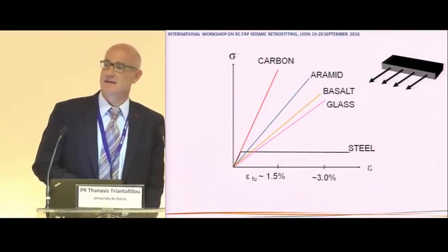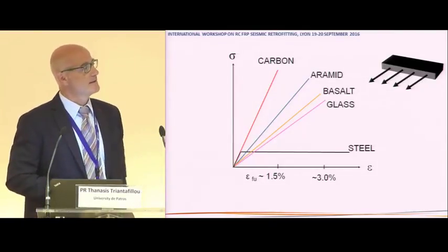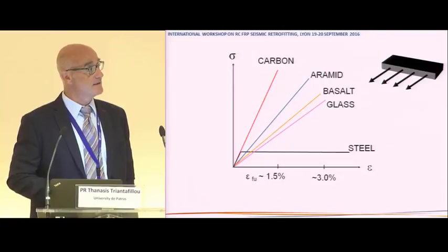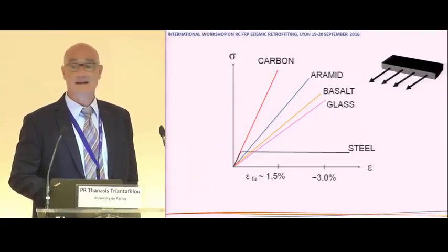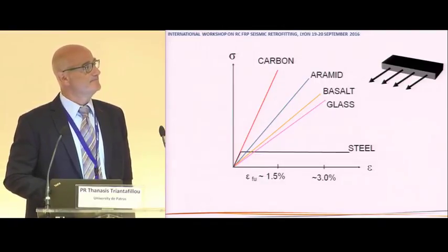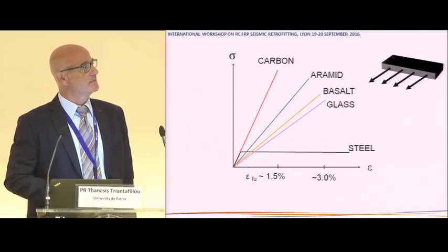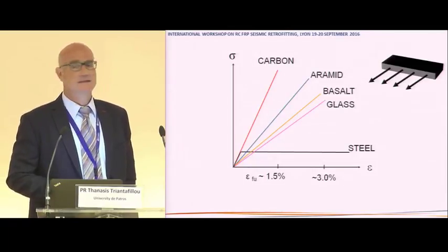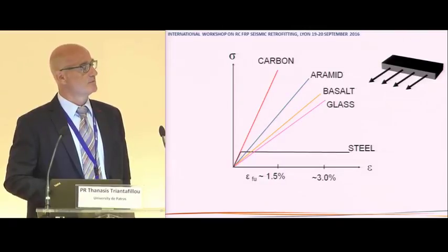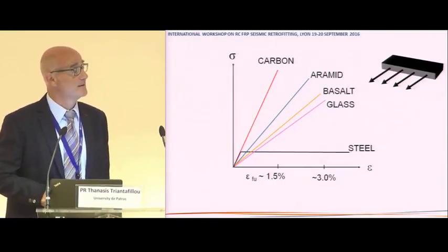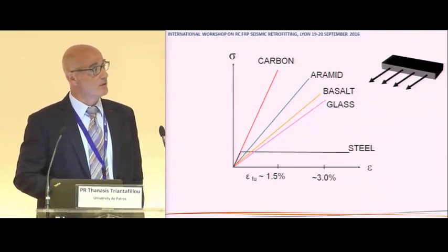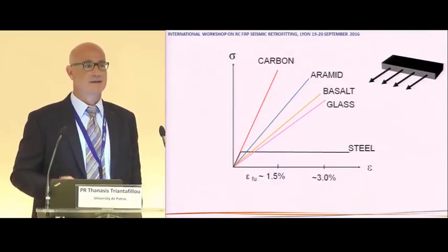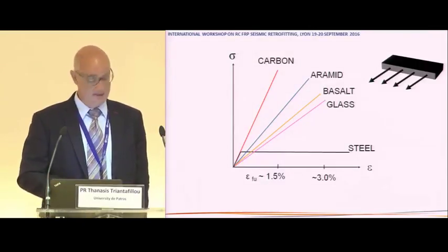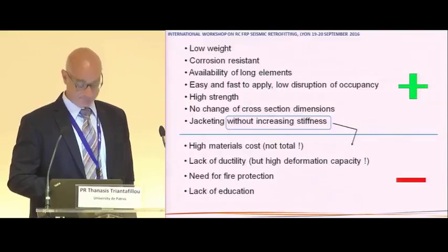If there is one thing that an engineer should know about these materials, it is that fibers behave linear elastic all the way to failure, unlike steel, mild steel. And depending on the type of fiber, we can have an elastic modulus from 70 to 230, even more, even up to 600 gigapascals. And of course, loads are only carried by the fiber. So our material is not isotropic as in the case of steel.